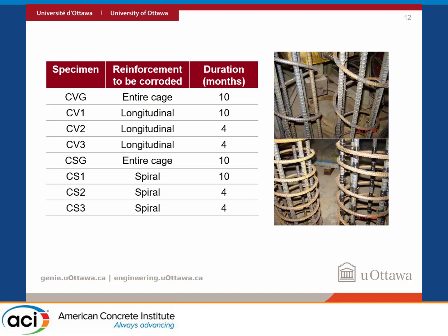So for the CV type columns, we used a shrink tube to isolate the spirals from the longitudinal reinforcement. For the ones where we were corroding the spirals, we used electrical tape at the contact points along the reinforcement. We had LVDTs to measure the deformation of the column.